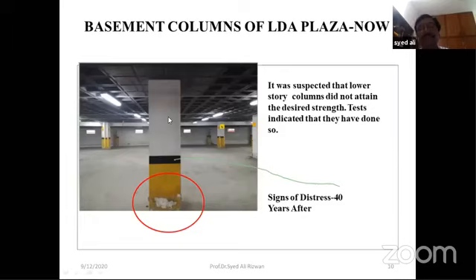required strength, which was, I think, around 6,000 PSI. And 6,000 PSI concrete at that time was quite a high strength concrete. Even now, even ACI code says that if f'c is more than 6,000 PSI, it should be classified as high strength concrete. But,